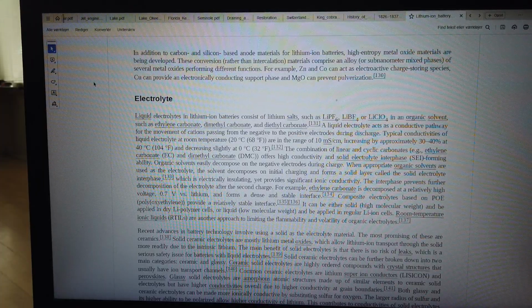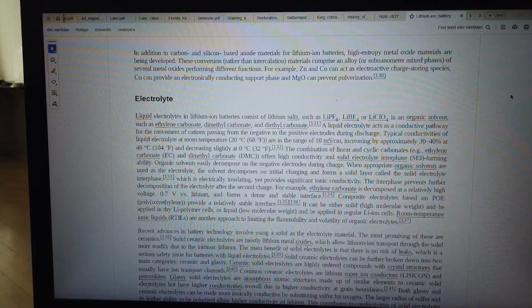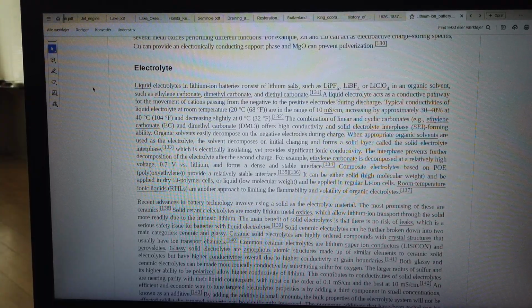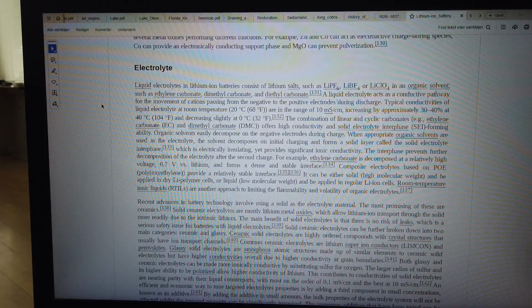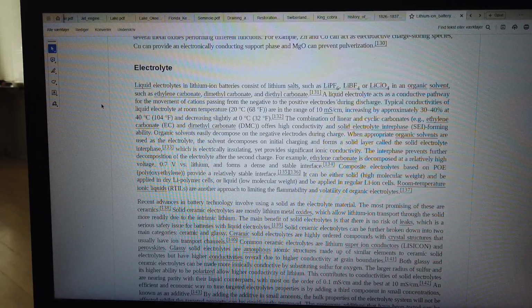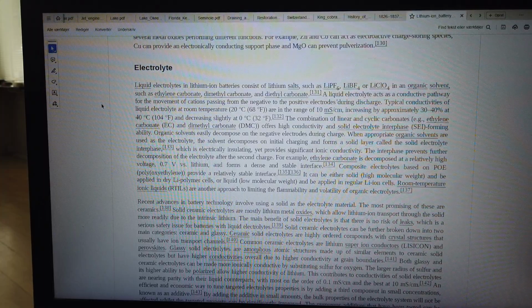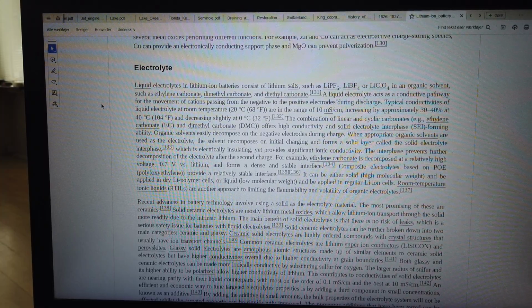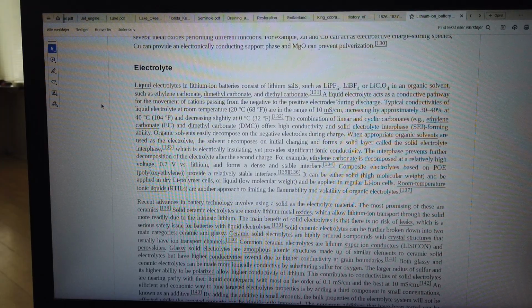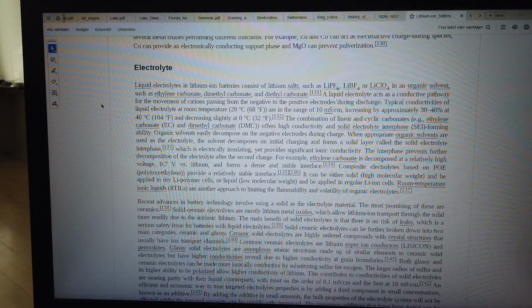130. Electrolyte. Liquid electrolytes in lithium-ion batteries consist of lithium salts, such as LiPF6, LiBF4 or LiClO4, in an organic solvent such as ethylene carbonate, dimethyl carbonate, and diethyl carbonate. 131. A liquid electrolyte acts as a conductive pathway for the movement of cations passing from the negative to the positive electrodes during discharge. Typical conductivities of liquid electrolyte at room temperature, 20 degrees Celsius, 68 degrees Fahrenheit, are in the range of 10 mS/centimeter, increasing by approximately 30–40% at 40 degrees C, 104 degrees Fahrenheit, and decreasing slightly at 0 degrees Celsius, 32 degrees Fahrenheit.